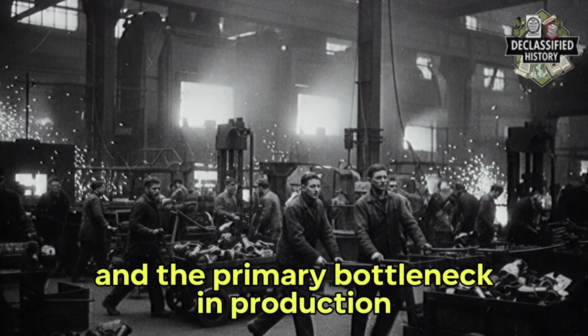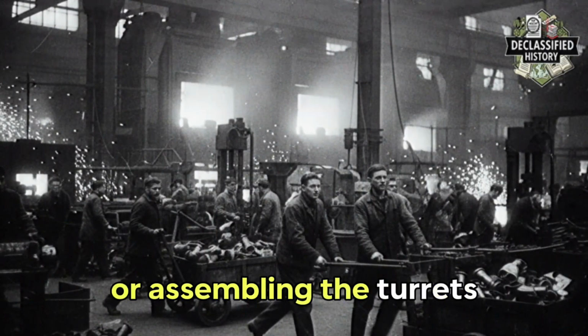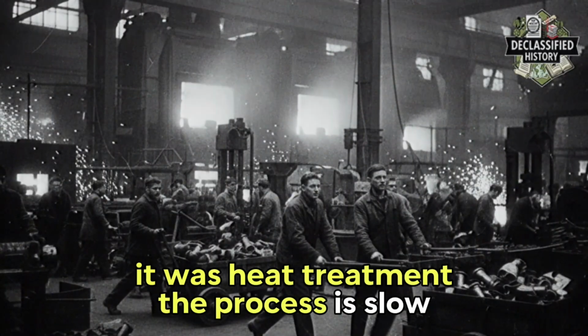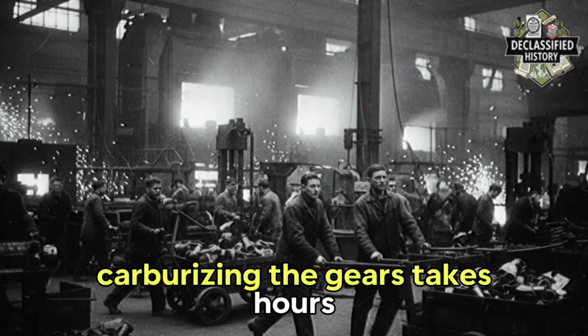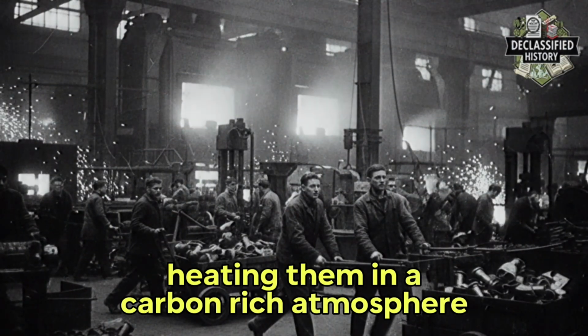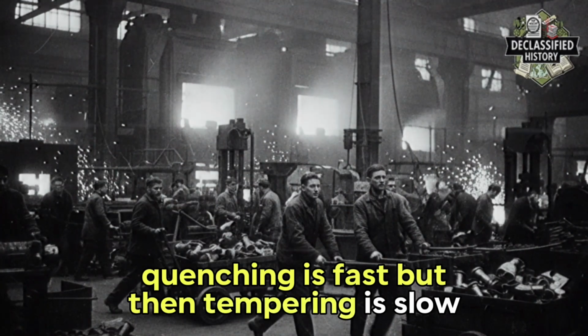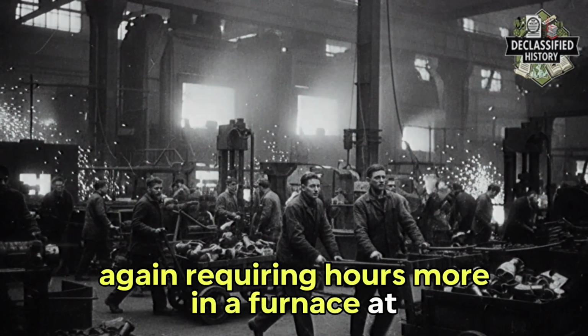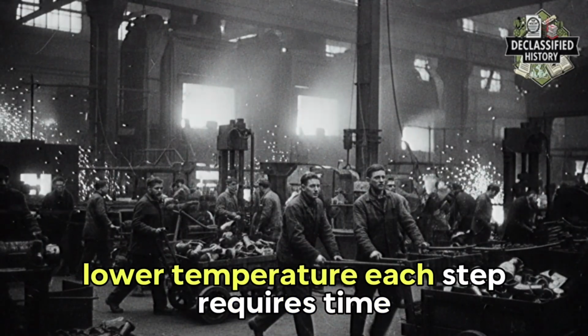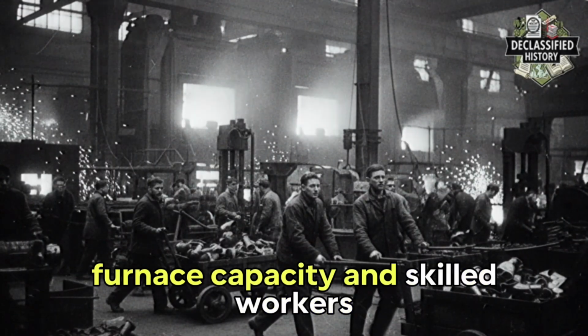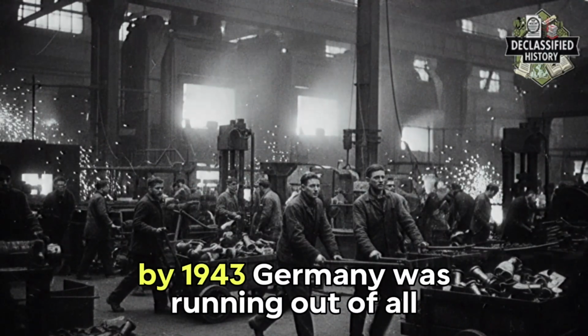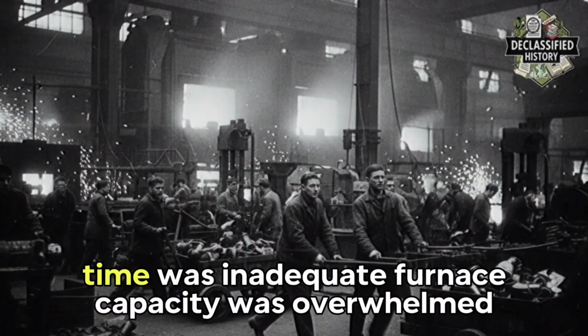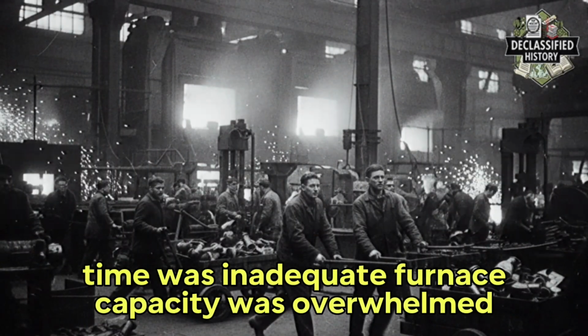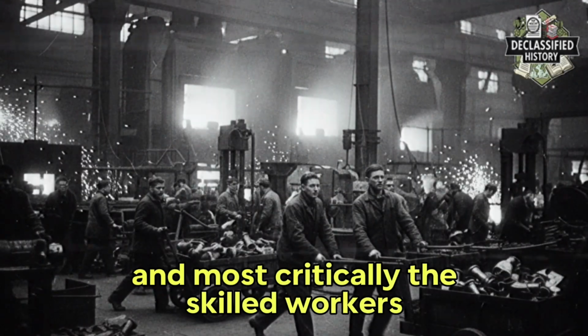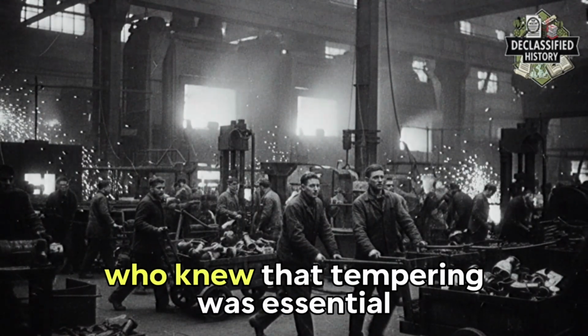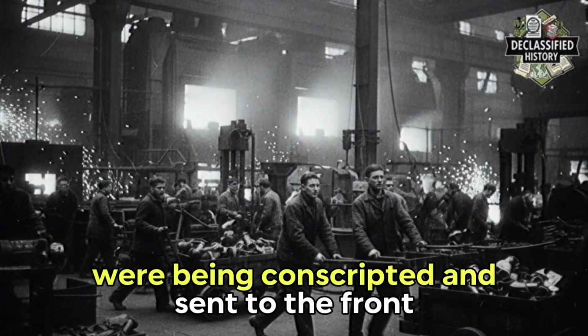And the primary bottleneck in production was not welding the hulls or assembling the turrets. It was heat treatment. The process is slow. Carburizing the gears takes hours, heating them in a carbon-rich atmosphere. Quenching is fast, but then tempering is slow again, requiring hours more in a furnace at a precise lower temperature. Each step requires time, furnace capacity, and skilled workers. By 1943, Germany was running out of all three. Time was inadequate. Furnace capacity was overwhelmed. And most critically, the skilled workers who understood the nuances of metallurgy, who knew that tempering was essential, were being conscripted and sent to the front.